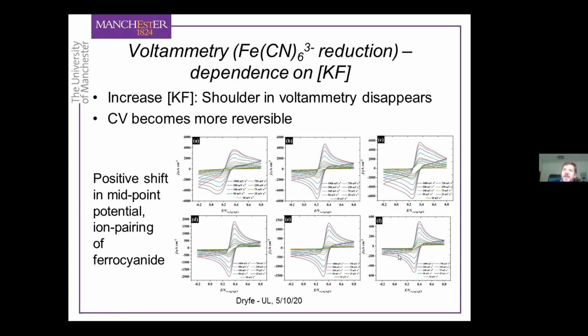That's easy to explain. Obviously, as we add more and more salt, the solution becomes more and more viscous, so the transport of the molecules slows down, hence the reduction in current. But the other thing that changes is the quality of the CV. We get CVs that look quite messy, not exactly electrochemically reversible, and with a shoulder in them at the low electrolyte concentrations. But those CVs become much more reversible, and the shoulder disappears as we go to the highest electrolyte concentrations. We get really pretty, more or less classical voltammetric responses by going to these very high electrolyte concentrations.